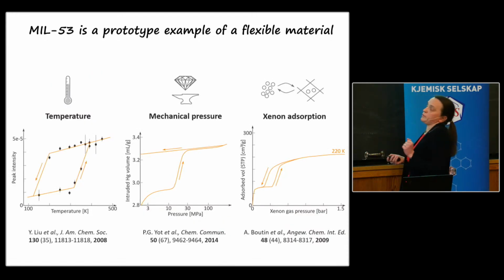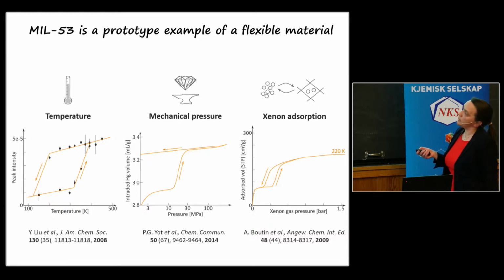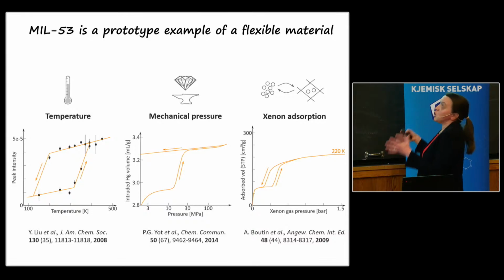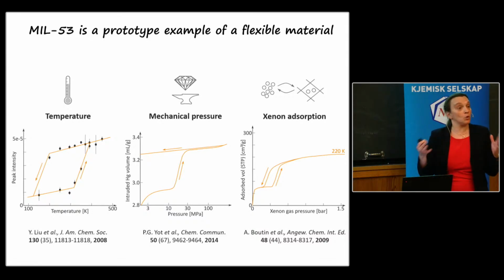Experimentally, you can try to follow that. So basically, here you can try to measure also the volumes, let's say, or the adsorption isotherms in terms of the stimulus. So like, for example, here it is in terms of the temperature. So we can see this is closed pore phase, and then it can open, and then it maybe can return. We can also see for pressure, so that you have these typical hysteresis curves. Also for gas adsorption, we can see that we have typical hysteresis curve. So that is what they can clearly observe experimentally, whether the material breathes or not, whether it opens or not.